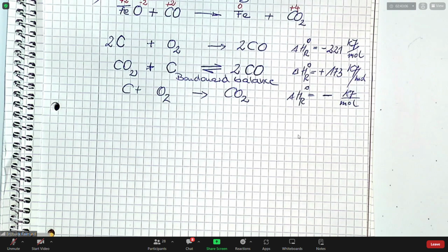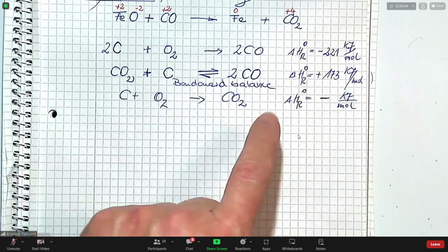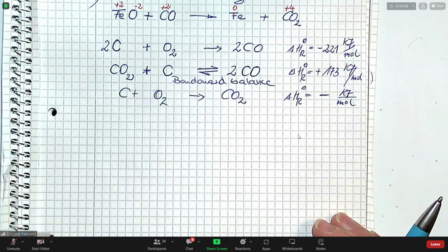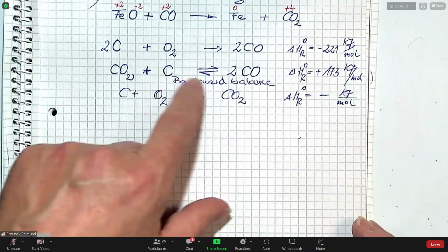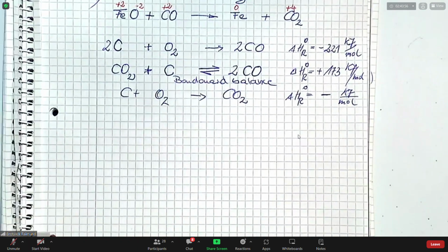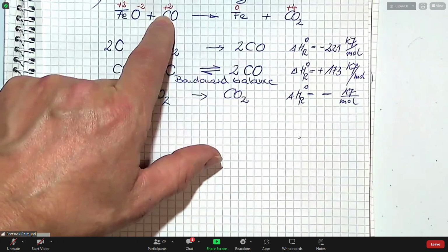First of all, we need the CO for the reduction of the iron oxide. But you have to be careful. Carbon monoxide is not healthy. It's poisoning, because if you inhale it, you die. The concentration of CO must be below 30 parts per million in the atmosphere to be safe. If you have more, you can die, because it blocks the transport mechanism in the blood for the oxygen. That's why sometimes there were problems in the steel industry, and Mr. Boudouard found out that CO is built as an intermediate. So the iron is reduced, the carbon is oxidized.